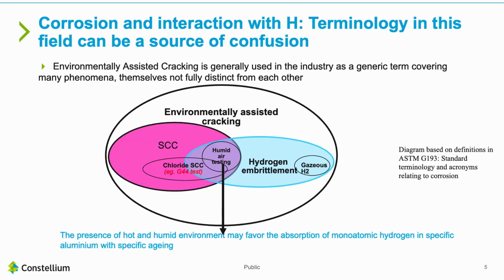If we then consider that we may have hydrogen in a monoatomic state, we have to consider environmental assisted cracking. And it's a general term. It englobes hydrogen embrittlement either with gaseous hydrogen or humid air, or also hydrogen coming from corrosion. So there is an overlap of corrosion and hydrogen embrittlement terms. And we will have a look at the common part that can be tested through stress corrosion trials under humid air or with chloride presence that will enhance the decomposition of water and enable the hydrogen to go inside the metal.